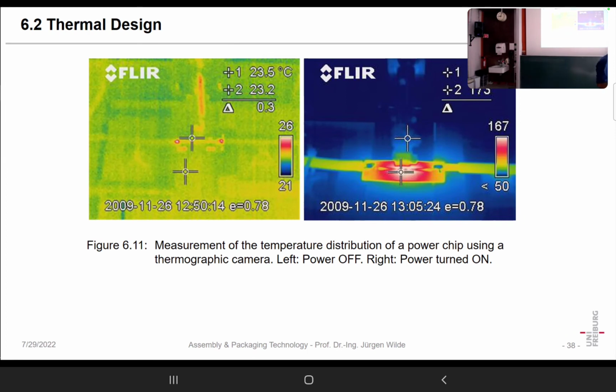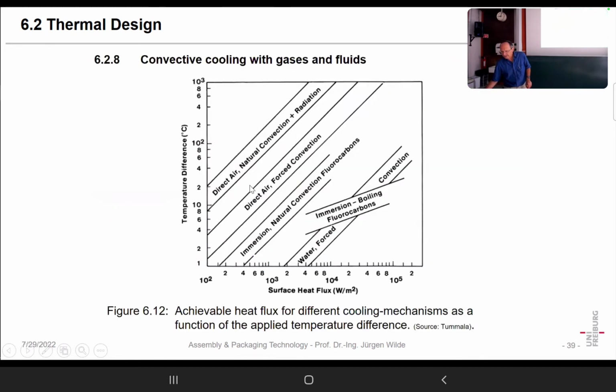And so in that way, we had a master thesis doing that. If you have some harmonic going in and some harmonic going out, you can have a phase shift. And from that phase shift, for each pixel, you can again make an image. And so you get the so-called phase image, not the temperature image. And the phase image can show you clearly if there is, for instance, a damage in temperature cycling also. So that's very interesting. And so one of my PhD students and one of my master students, they developed that method.